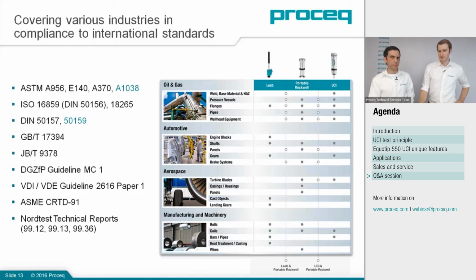There are special requirements on the test blocks. So actually, UCI is measuring in Vickers scale, and you can use Vickers hardness test blocks. But as we mentioned during the webinar, it is not a stationary method. It is a quasi-static method, and it requires certain thickness and certain mass of the test piece. And therefore, also for the test blocks, it is recommended that it has a certain size, and it should be approximately 80 millimeter in diameter and more than 15 millimeter thickness.